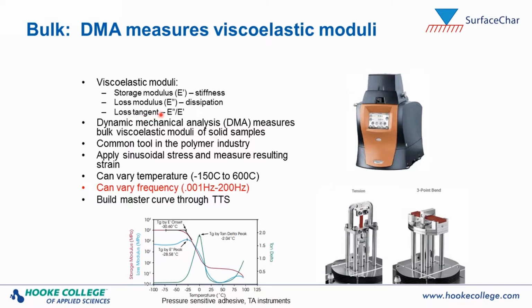And again, these are moduli that are frequency dependent, so they change as a function of how quickly you measure them. So in the bulk, we use dynamic mechanical analysis to measure the viscoelastic moduli of solid samples. This is a very common tool used in the polymer industry, where you apply a sinusoidal stress and you measure the resulting strain. Typically, the bulk DMA measurements are done as a function of either temperature over a pretty wide range or frequency also over a wide range, but notice what that range is. We're talking about 0.001 hertz to 200 hertz. This is low frequency relative to what AFM measurements do.